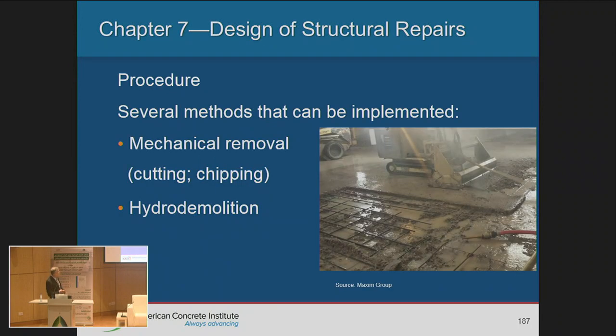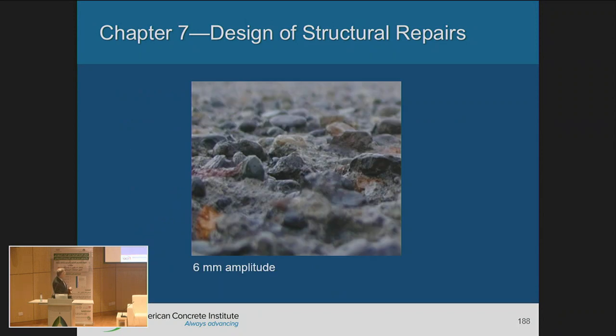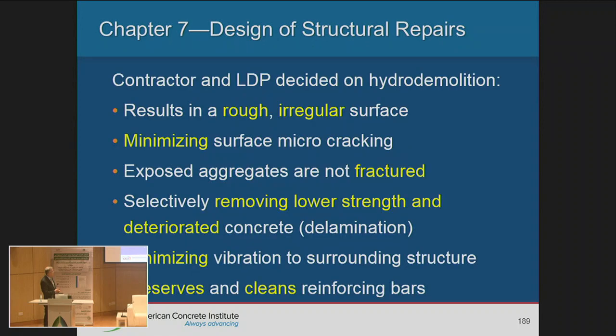Or you can use hydro demolition, when you apply high-speed water on your surface. This one has the advantage, if you look at the surface, that it does not cut through or damage the aggregate, and does not create micro cracking. You'd like to have that aggregate so you get a good grab between the new concrete and the existing concrete. So you have that amplitude. And as I mentioned, there's no micro cracking there.